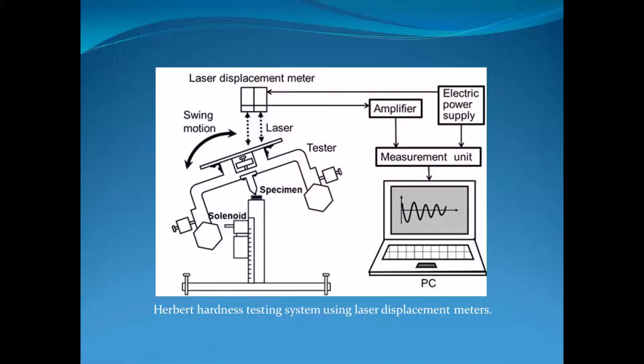Vertically above the indenter, a screw-operated top weight. By moving the weight vertically, the center of gravity of the entire tester can be raised or lowered above the center of the cylindrical indenter. For hardness testing, the vertical position of the center of gravity is adjusted so that a single time period of device oscillation is 20 seconds on an artificial sapphire plate.